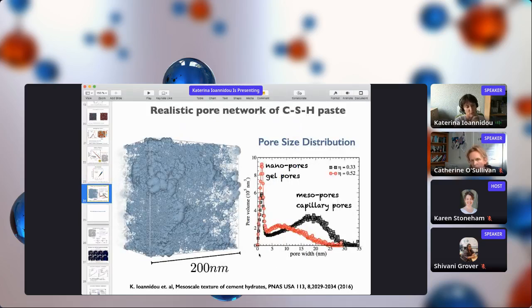It's a key point for cement: the porosity that it has, the sizes of pores, and its connectivity. Here you can see the pore network that we get from the simulations, and here is the pore size distribution. We have a peak of nanopores of 1, 2, 3 nanometers. These are called gel pores in the cement community, and they have been observed with NMR experiments. On the scale of 5 to 50 nanometers, we have the capillary porosity, which has a continuous distribution of sizes with a long tail, and this is what is usually observed with nitrogen adsorption-desorption experiments. So this was another point that we could connect together with these experiments.